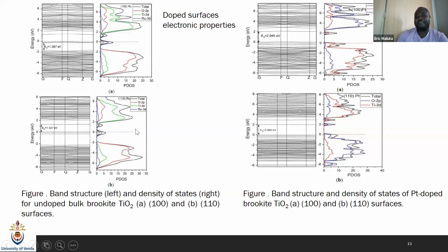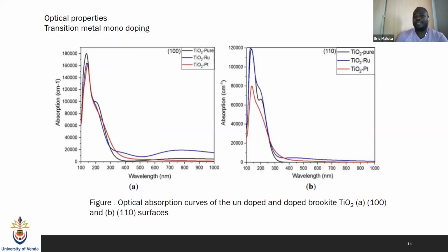the surfaces can, apart from absorbing in the ultraviolet, now absorb in the visible region and towards the near infrared. And this is the optical property where we are just looking at the absorption of the pure surface. If you look at the two figures on my left and the right, the pure surface is higher here, but then it comes down around 400 nanometer. But when it's doped with ruthenium and platinum, then we are changing its absorption.